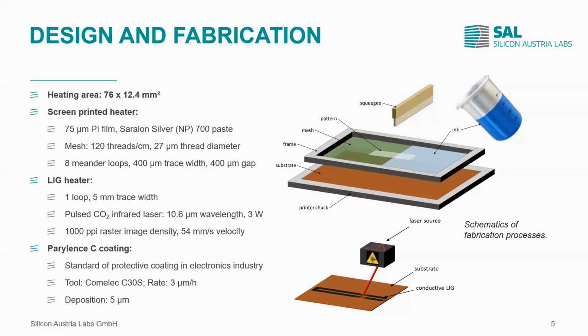Further, a Parylene-C coating was attached. Why Parylene-C coating? Well, Parylene-C is known to be something like the gold standard material for coating in the electronics industry, and this now for several years. So we put the Parylene-C coating on top with 5 microns thickness with a deposition rate of 3 microns per hour.